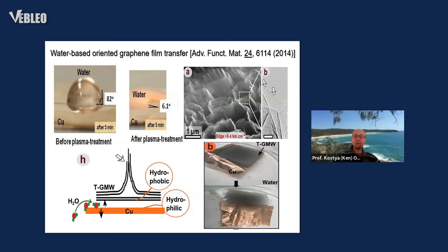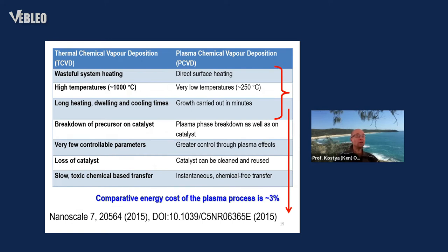One very interesting fundamental effect of interactions of plasma with both the catalytic surface on which the nanostructures grow and the nanostructures themselves is the unique changes in hydrophilicity and hydrophobicity, when it becomes possible to actually separate the grown layers of these vertically oriented graphenes from the copper foil on which we grow them using plasma. And this unique process actually has created very interesting opportunities, not only to produce the graphene structures at much lower temperatures, which could be as low as 250 degrees versus typical temperature of the order of many hundreds of degrees and up to 1,000 degrees characteristic to thermal chemical vapor deposition.